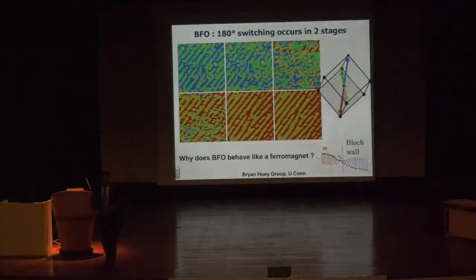A few years afterwards, we were doing an experiment which came out in this Nature paper where we were saying, if I switch the ferroelectric polarization for bismuth ferrite, how does this switch? And this is a set of experiments which is actually still baffling, and I'll tell you why it's baffling. What these are ferroelectric domains. Think of domains which are rotated by 71 degrees. So these look like the slats on the surface here.